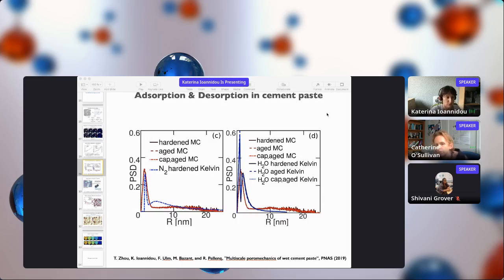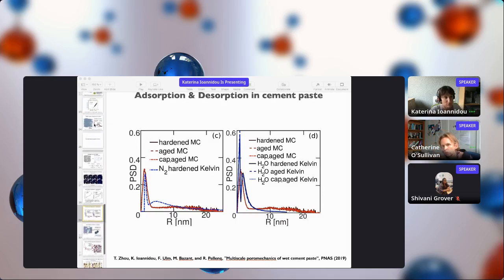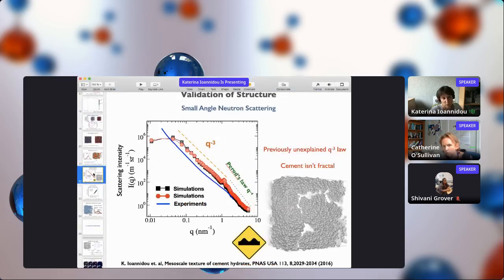Yeah, exactly. So it's not that we like to use all this particle. For example, when I'm talking about cement, which I know well from the experimental literature, a point why we had to use so many particles and go to such large scale is that if we want to connect with scattering experiments, we need 2 orders of magnitude. We can see here from the signal that we have heterogeneities at 2 orders of magnitude.